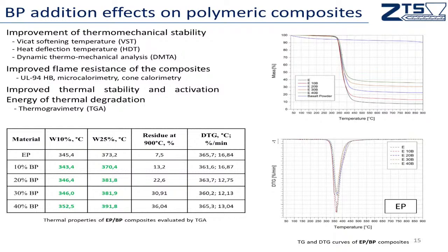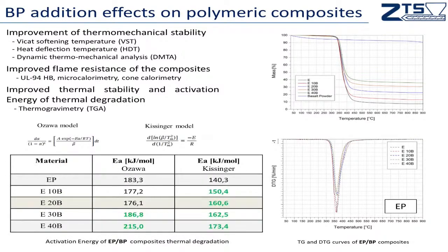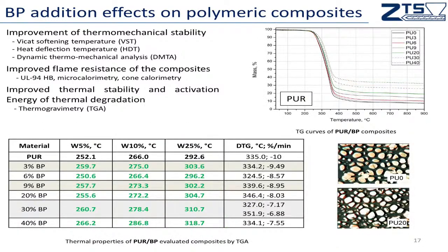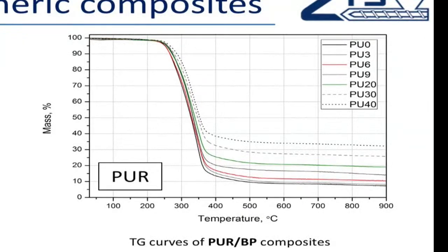And if we move to another slide, we can see that not only the temperature characteristic for the mass loss was increased, but also the thermal degradation kinetics evaluated by different models, including the Ozawa and Kissinger models presented here. The activation energy of the degradation was also improved. So this is really good information for us. Even if we check on the next slide the results of the thermal degradation measured by thermogravimetry for polyurethane foam, the material that is broadly used in civil engineering for thermal insulation, we can see that the thermal stability is significantly improved.